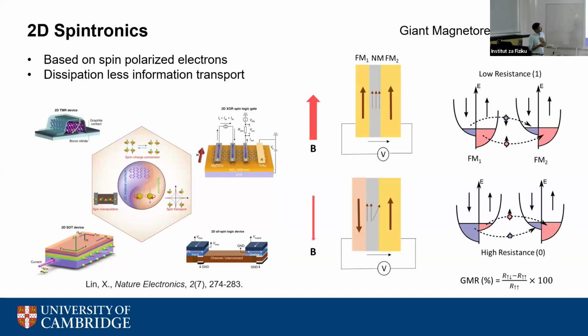And just to remind you, what is GMR? GMR is a phenomenon which was discovered, I think, 20, 30 years ago, where people showed that if you have two ferromagnets and you insert a non-magnetic layer, then the resistance of this channel between the two ferromagnets depends on the alignment of the spin. So if you have, let us say, a parallel spin orientation, you have one resistance state, and if you have anti-parallel spin orientation, you have a different resistance state. And this is the foundational idea for most spintronic and magnetic devices which have progressed over the last few decades.